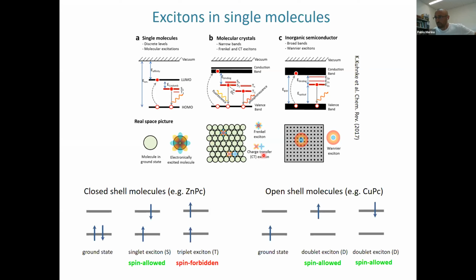And today I will be talking about zinc phthalocyanine and copper phthalocyanine, and what I want to show you is that for closed shell molecules, you can have singlets and triplets. You see here that when we promote one electron from the ground state to the first electronic state available, it can have either an anti-parallel spin, and then you have a singlet exciton, and this will be spin allowed to decay into a photon, or it can be parallel, and in this case it will be spin forbidden to decay, and this will take much longer to decay as a photon, actually through an intersystem crossing, and this will be a phosphorescence event.